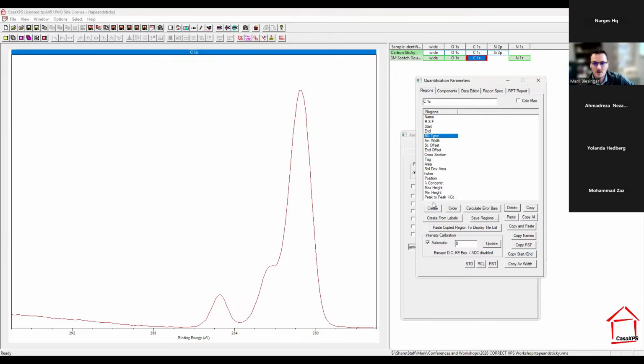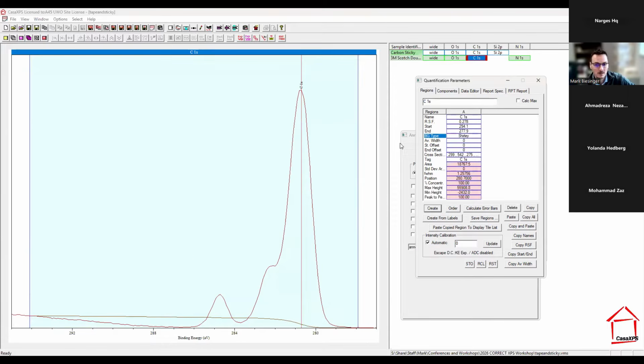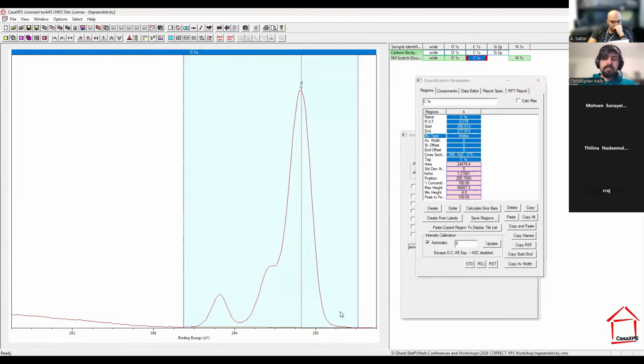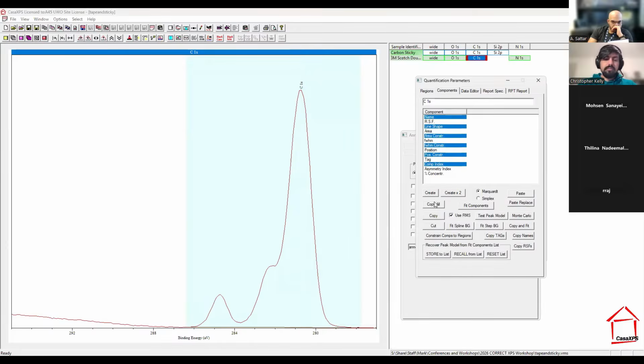So the first thing we do is create a background. In this case, it's a Shirley background. There are other backgrounds possible, but a Shirley is a very commonly used background that for most cases is sufficient. And we're going to set our endpoints across that background so that we have a nice background across there. Then we'll go into components, and we're going to create a peak.